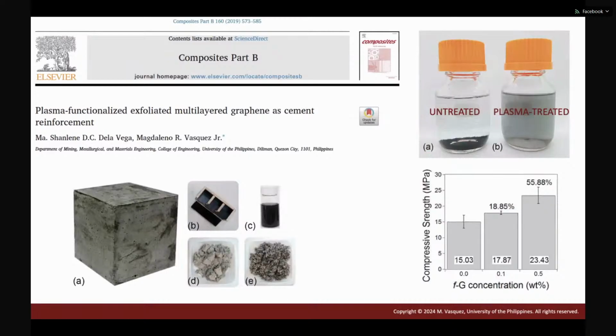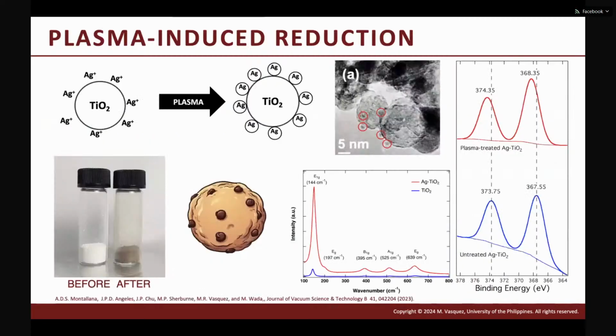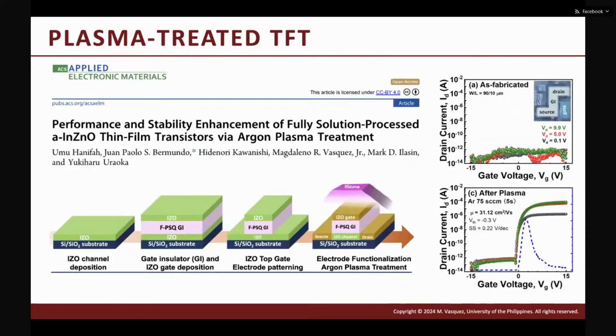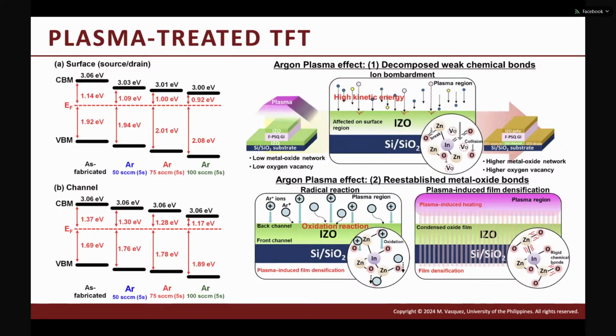This one also is graphene, and we also use graphene, plasma treated graphene, to improve the strength of cement. So this one is plasma induced reduction. So we can use plasma to form metallic nanoparticles such as silver, and we use this to couple with titanium dioxide. And we use this as a catalyst. This one is plasma treatment of TFT, and we're able to use this to improve the switching capability of TFTs. And you can also use this to tune the Fermi level of your TFT or the material. I think here this is IZO.